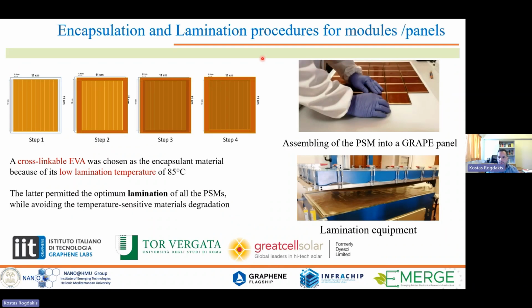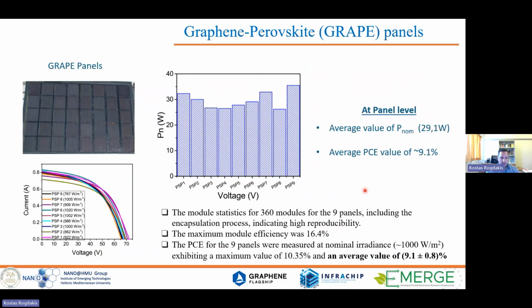Then with our colleagues, we implemented the lamination. They used EVA as a material, and the goal was to use the lamination temperature as low as possible. The maximum was around 85 degrees, although this low temperature at the end had a negative impact on the final lifetime stability of the panels that I will show you later. So we performed the lamination and then fabricated the panels. As I told you, we have 9 panels with an average PCE of 9%. This is the distribution of the output power per panel, around 30 watts on average.